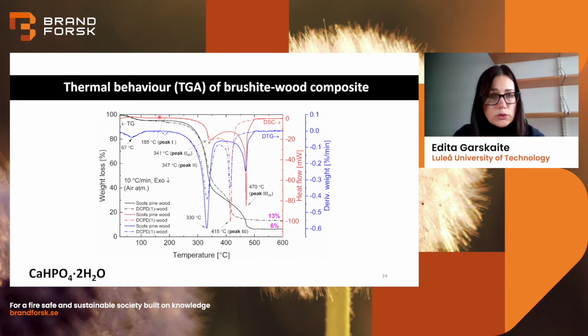But what we also observed is a small peak at around 185, which was not present in the pure unmodified wood. And that actually has to do with water release from the structure of the mineral.